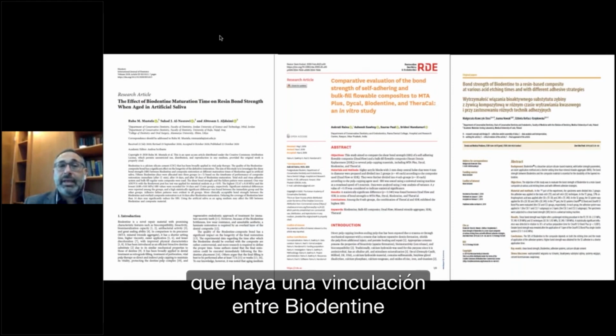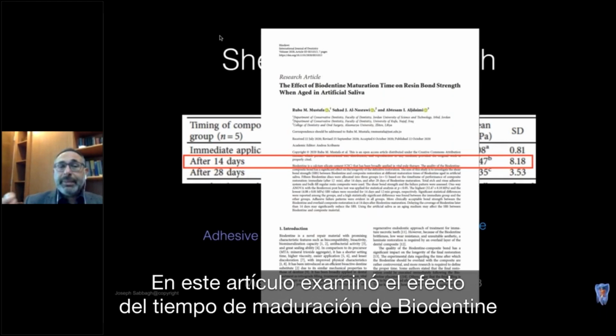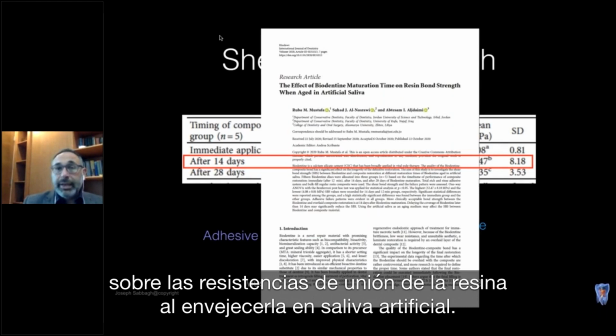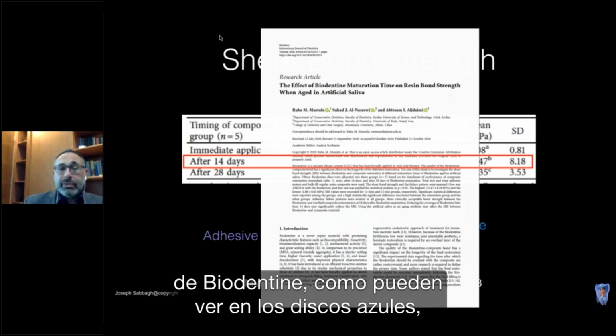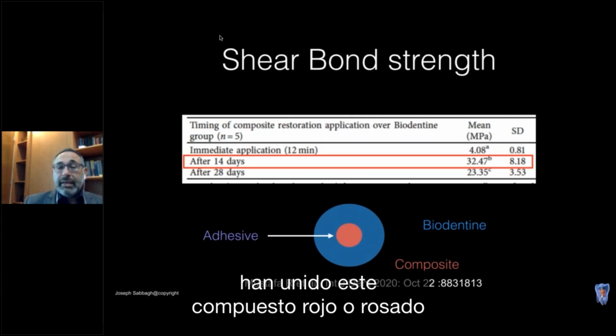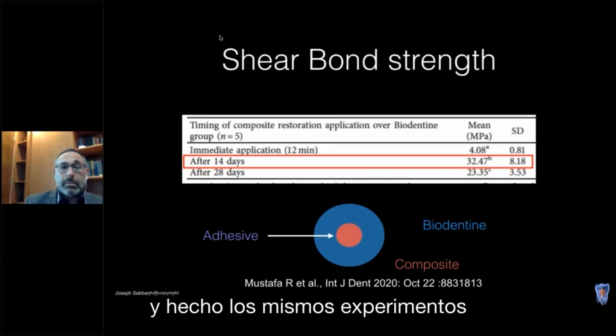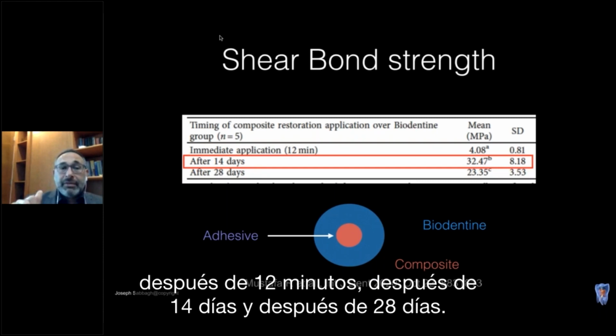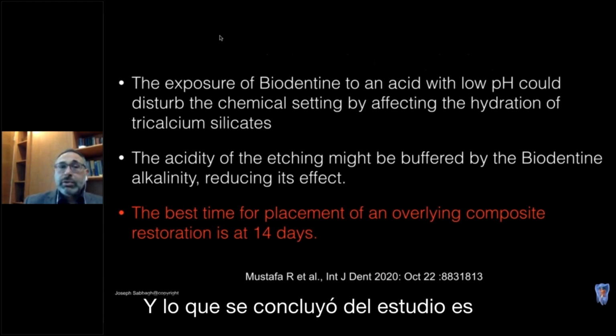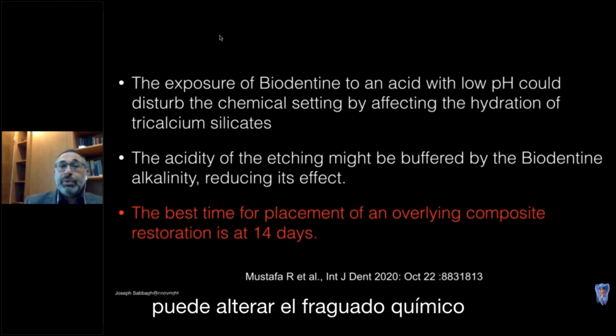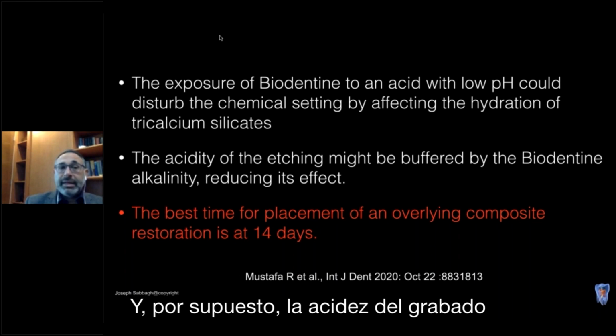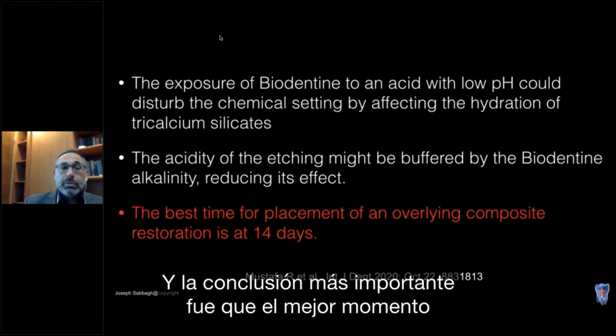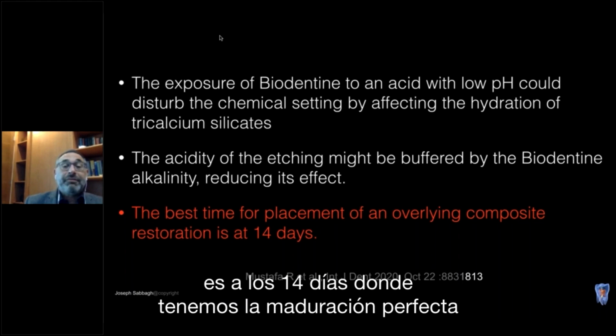Let's look closely at the first paper. This paper examined the effect of Biodentine maturation time on the resin bond strengths when aged in artificial saliva. What is interesting is that they made samples of Biodentine, as you see the blue discs, and on those discs of Biodentine, they bonded discs of composite in red or pink color, and they did the same experiment after 12 minutes, after 14 days, and after 28 days. And what was concluded from the study is that the exposure of Biodentine to an acid with low pH could disturb the chemical setting by affecting the hydration of tricalcium silicate. And of course, the acidity of the etching might be buffered by Biodentine. And the most important conclusion was that the best time for placement of an overlying composite restoration is at 14 days, where we have a perfect maturation of Biodentine.